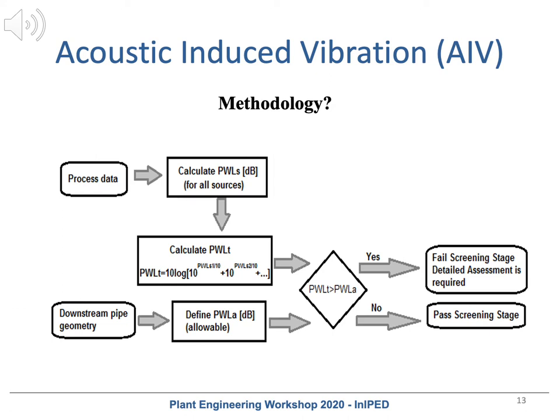All those elements that haven't complied with the screening stage are required to undergo a detailed assessment. The purpose of the detailed assessment is to predict the dynamic fatigue risk for piping identified as being of potential concern in the screening stage. The sound power level at each asymmetric discontinuity is calculated, taking into account attenuation due to the distance from the source and piping geometry. Once this calculation has been performed, it is identified which elements fail the screening stage and the detailed assessment, and which have passed. Once all this information is collected, the possible modifications are established, and the actions are taken into account in the design, as well as in the process data.